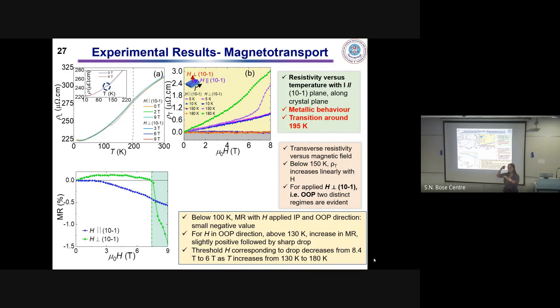However, the inter-ladder coupling between the Fe and Fe is antiferromagnetic. So what might be happening is that because of the application of a magnetic field in the out-of-plane direction, above a certain temperature there is a spin flop of the antiferromagnetic moments, and you see this kind of sharp drop here.